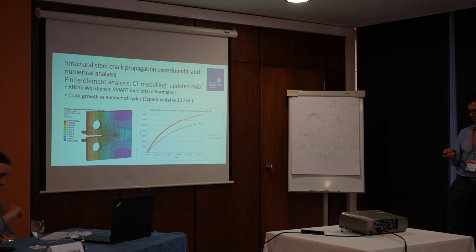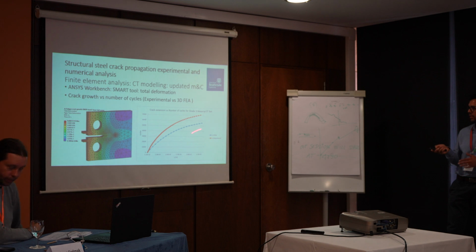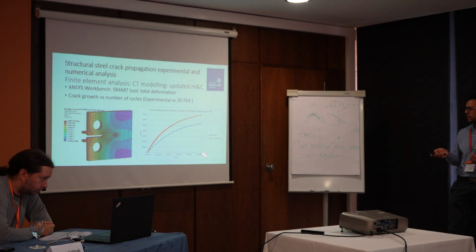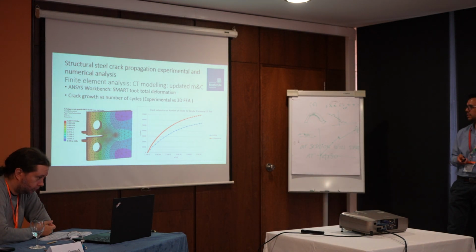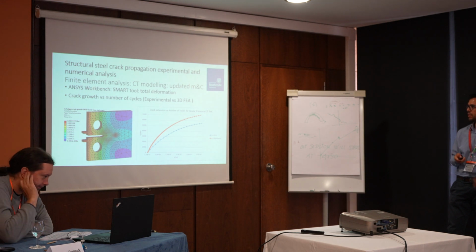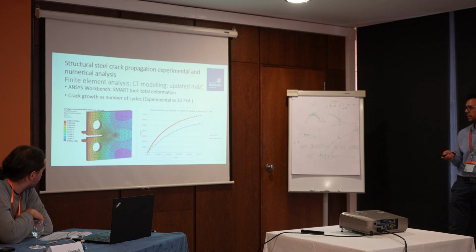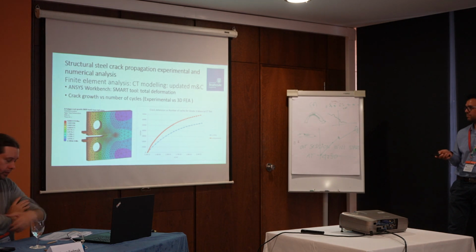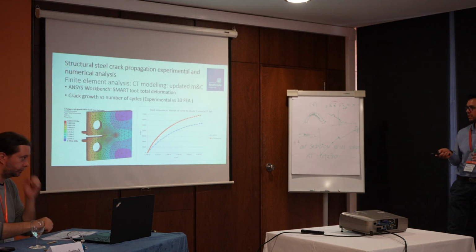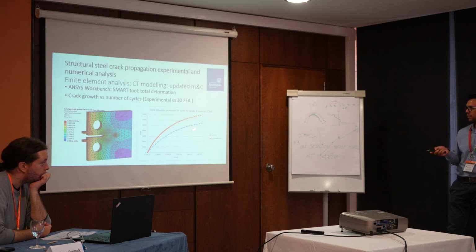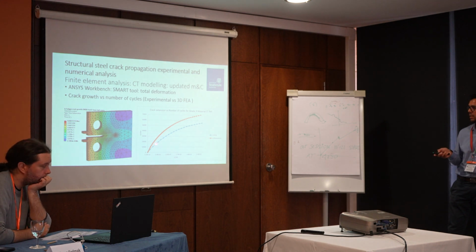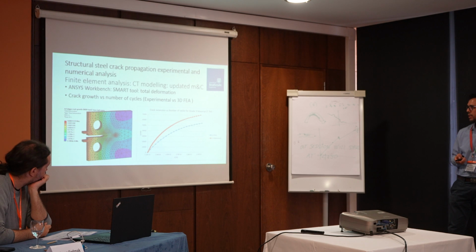Well, this is some of the results comparing the lab test results against the finite element analysis using the updated parameters for the Paris law. And here we can see that using the finite element analysis, we have certain differences, but the finite element analysis seems to be a little bit more conservative compared to the experimental data.